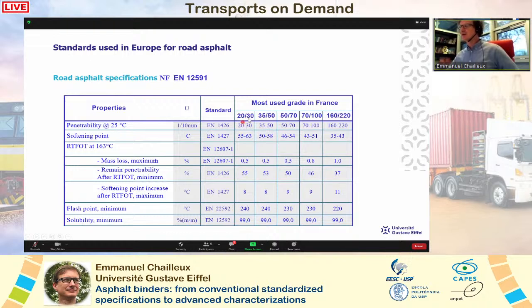The 20/30 is a very hard binder, and the 160/220 is a very soft one. The last one is used to make emulsion, for example, and this one is mainly used to make base course, structural course, not surface course. The most common one used in France is the 35/50, which is also quite hard. And you see that the penetrability is associated with a range of softening point.